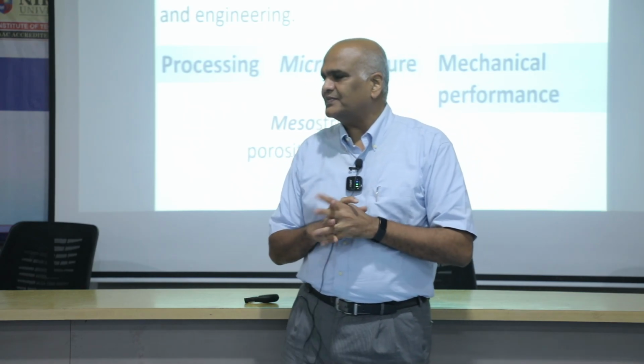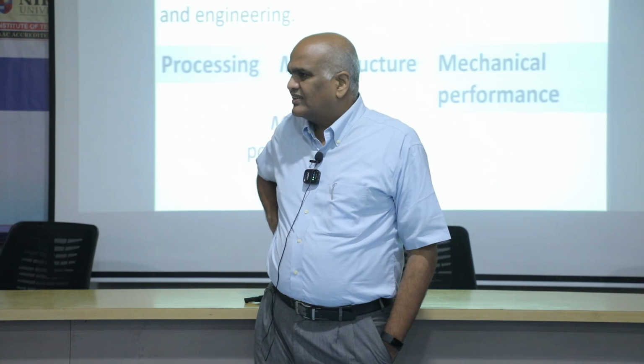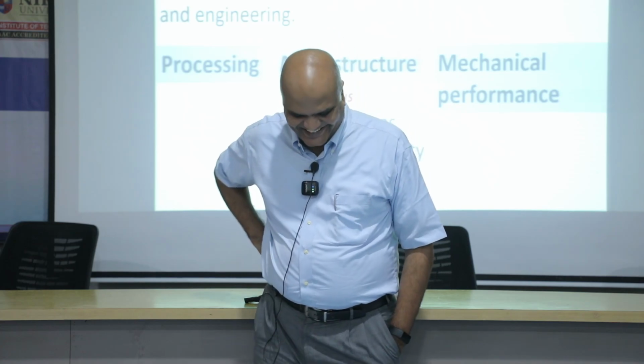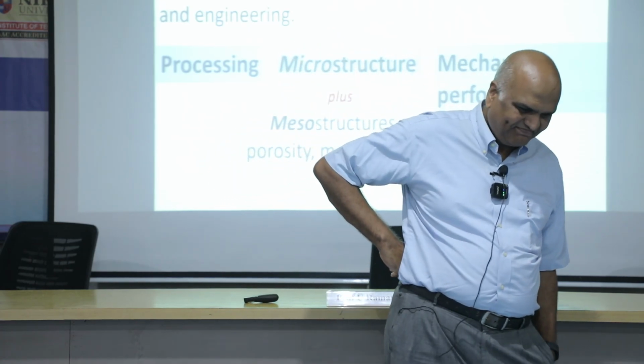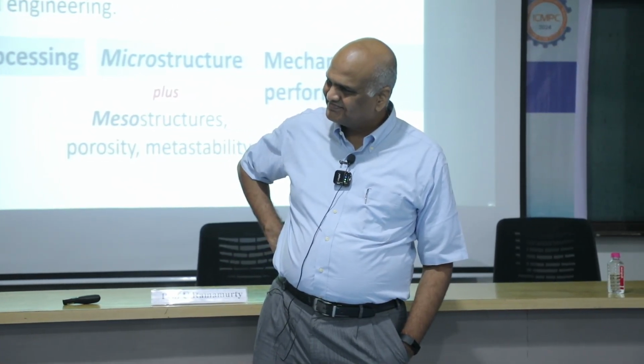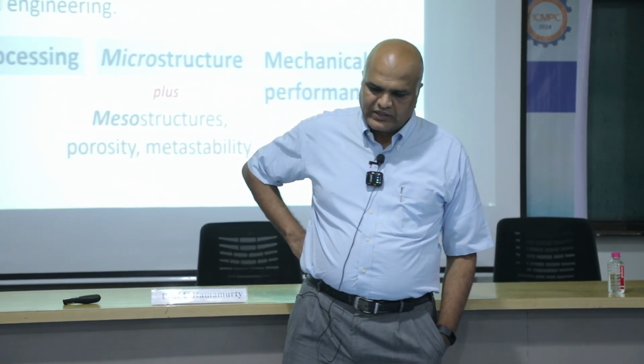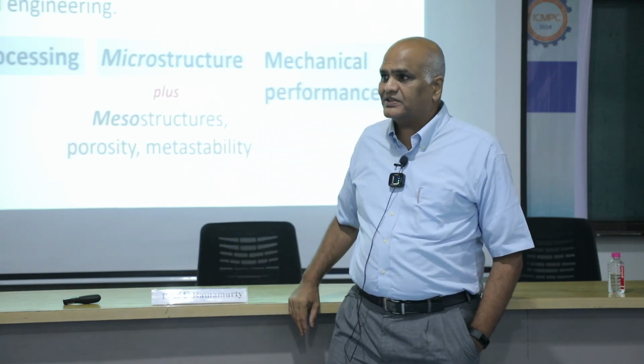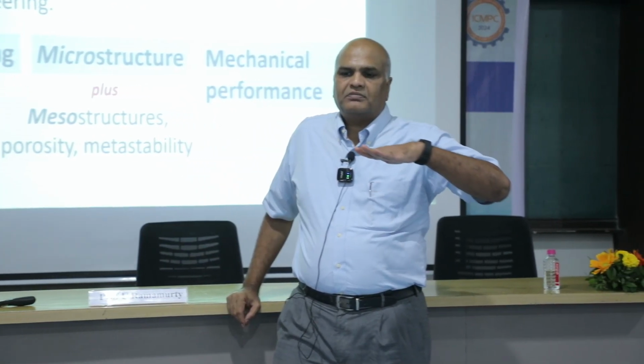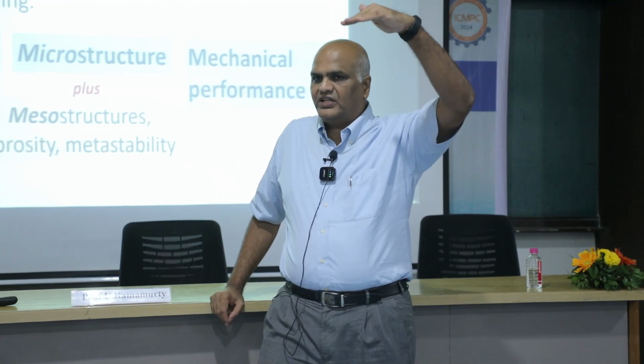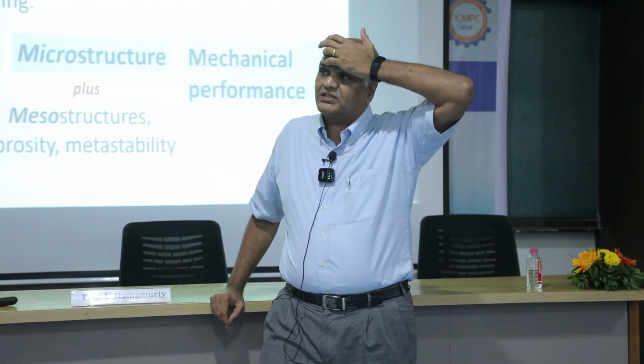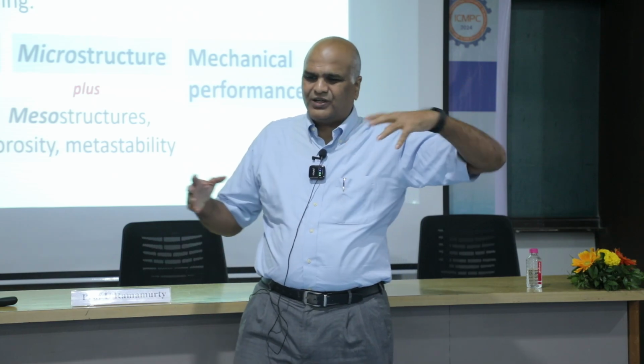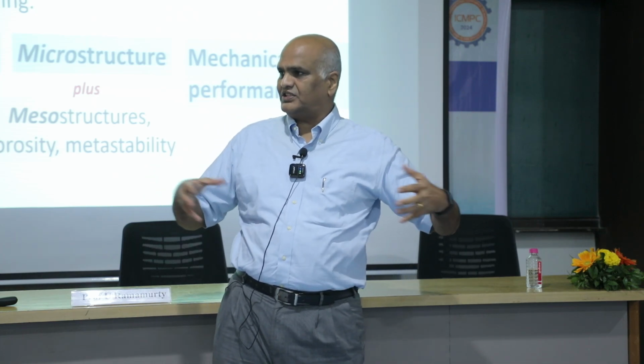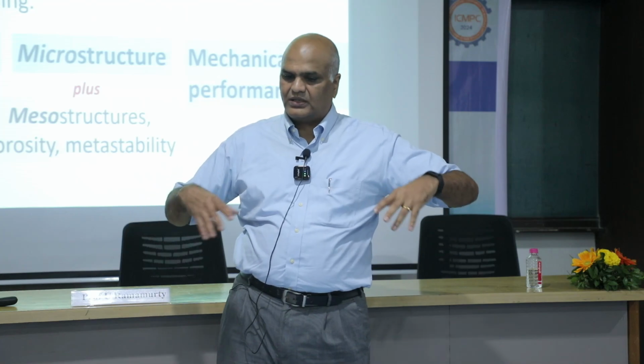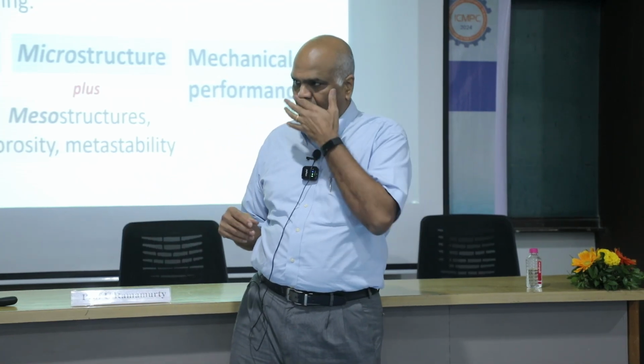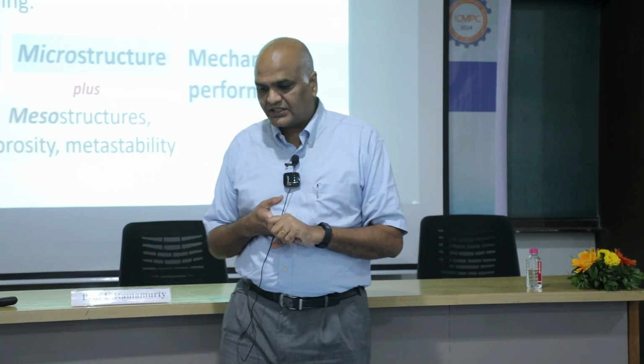I have one more question. Is the microstructure organized around the thickness of the part? Yes, layer by layer. So when we are doing the microstructural study, from where are we taking the segment? Some parts have a significant variation in microstructure from bottom to top. Essentially the heat gets built up. It's not all dissipated. So progressively as the heat builds up, there is a microstructural variation. You need to worry about it.